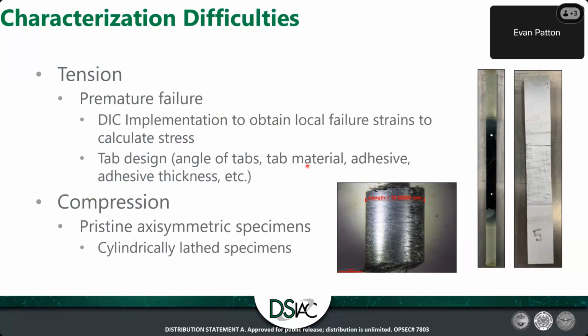Before I dive too much into the characterization results from the specimens that were pulled from that hydraulic press, I think it's important to highlight the difficulties of dealing with this material. And I shouldn't say that it's just prone to this material in general. It's just all composites. But I'd like to highlight specifically our tension and compression specimens led to a lot of premature failure in the tensile mode. And we saw that in essentially shearing in the gauge or in the grip areas from the Instron machine. The composite was so strong in the tensile direction that it would actually pull on the grips to the point where it crushes the composite in the tabbing area and would lead to a premature shear there.